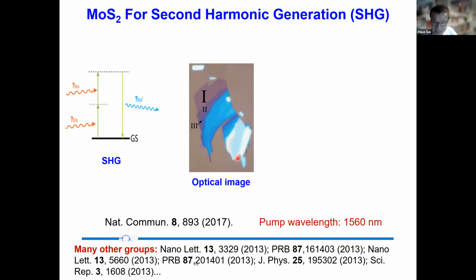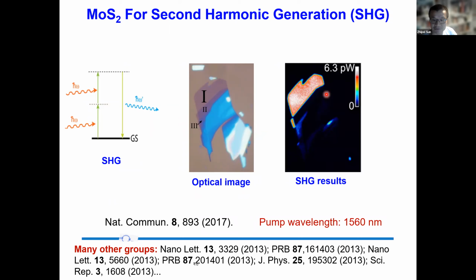This is our flake, and this is the second harmonic generation image we get. You can see here, we are able to get very high second harmonic generation with the monolayer, and also with the trilayer. But something very surprising: for the bilayer and also for the thick layer here, we couldn't get second harmonic generation. The reason is that the bilayer and the thick layer have a centrosymmetric structure, which doesn't have the second order nonlinear response, similar to the monolayer graphene.